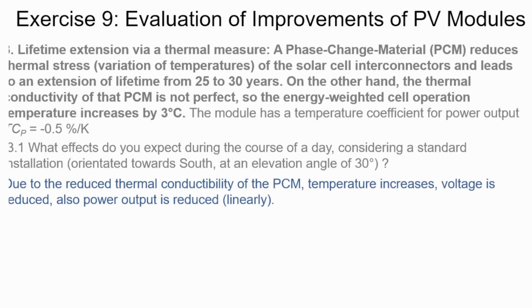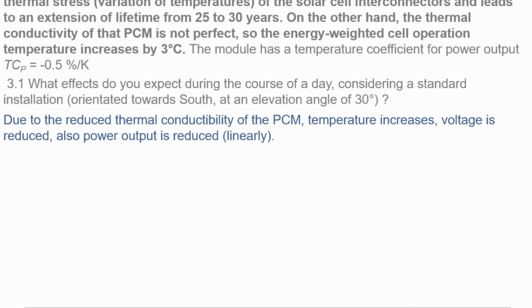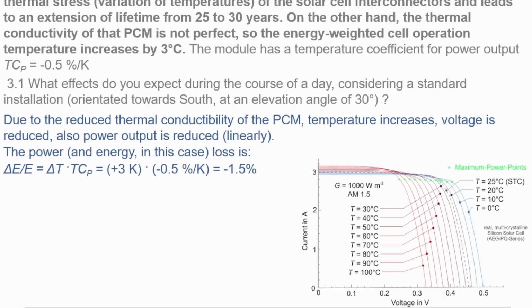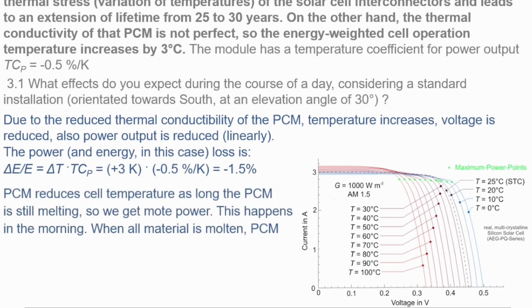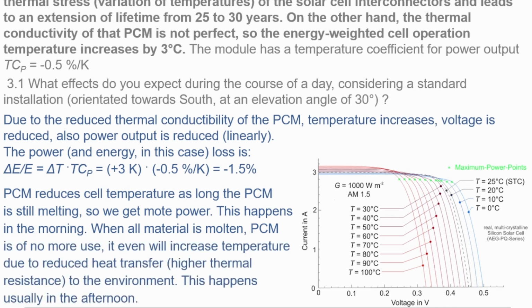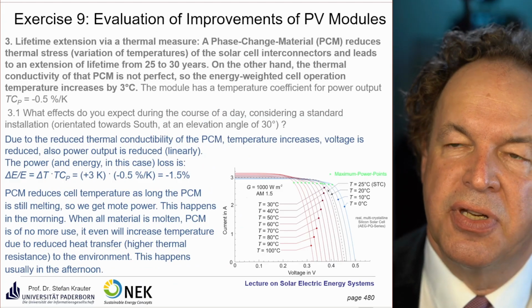So due to the reduced thermal conductivity, voltage is reduced and also power output is reduced, but linearly. So as you see here, this curve and this constant coefficient. And so for 3 degrees of temperature increase, we will have a power loss of minus 1.5%. So the PCM is reducing temperature as long as the PCM is still melting. So then we get more power. This happens in the morning. When all material is molten, the PCM doesn't have a positive effect anymore. It even will increase the temperature due to the reduced heat transfer, as this material has a higher thermal resistance. And this happens in the afternoon.